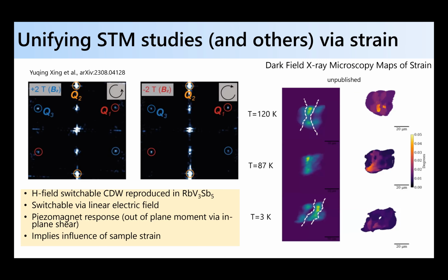All right. So one thing we can do is take a look at a nominally strain-free crystal with dark field X-ray microscopy. This is work done with Zahir Islam at Argonne at the Advanced Photon Source. All I want to show you is a real space image of strain in a sample. You can see these hot spots here where the strain is larger than these cold spots here. So there are these ribbons of strain that exist in most real materials. But these are particularly soft metals, and so you have strain fields that are baked into the system that we need to start learning how to control.